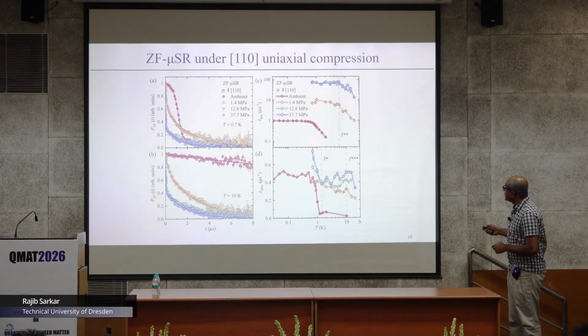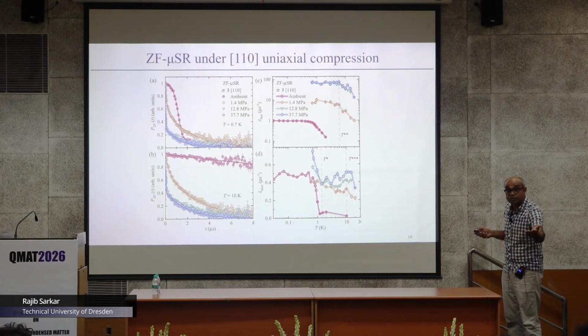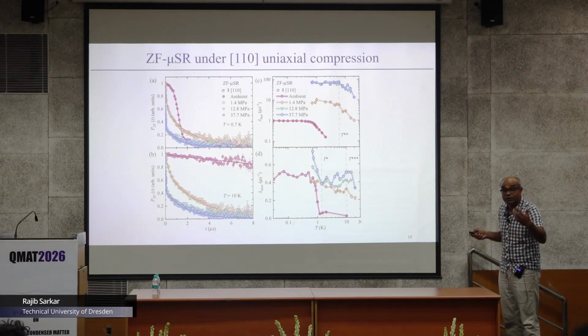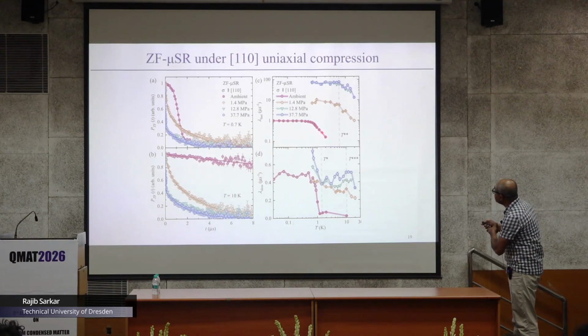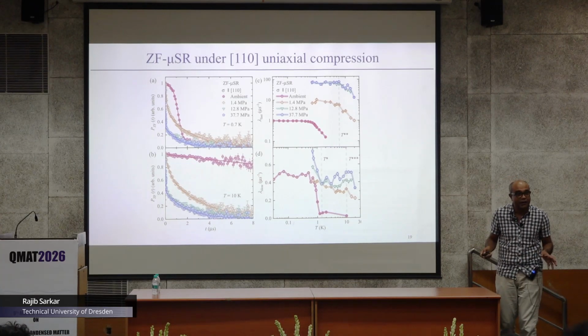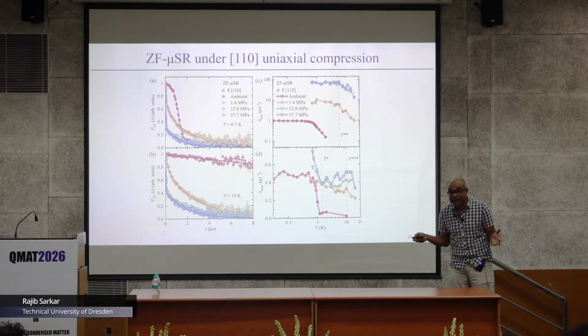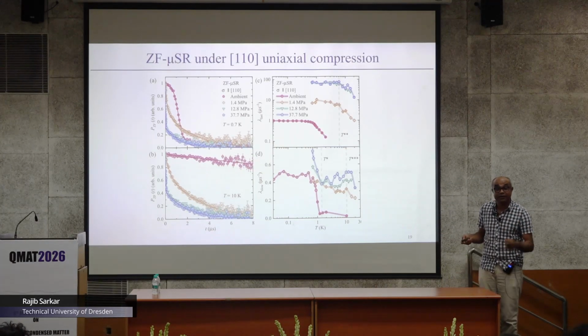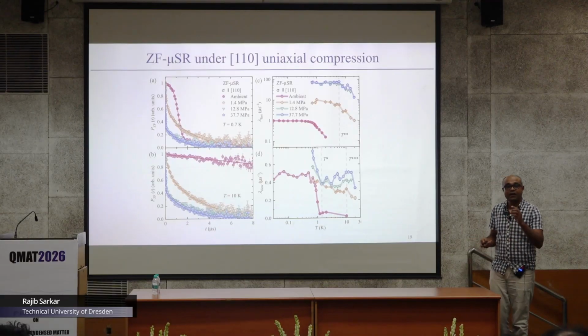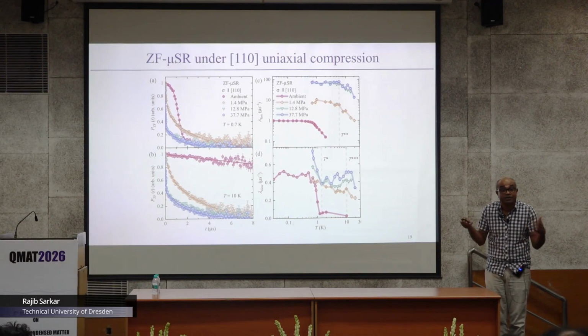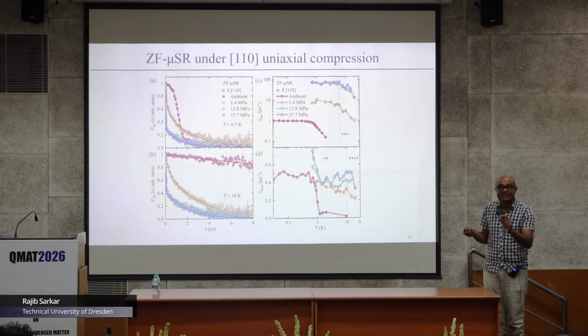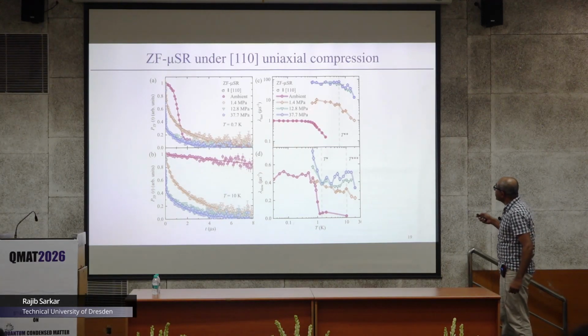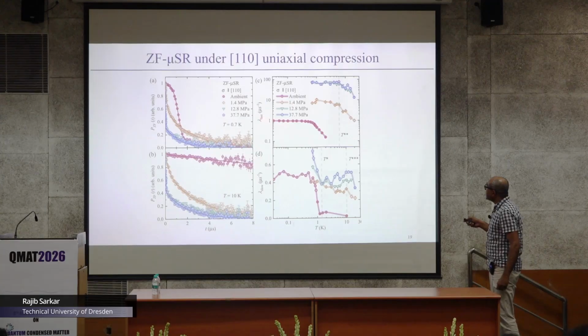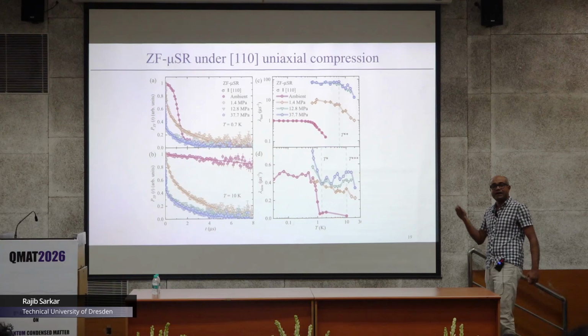And now if you really make a model and a fit, then you get a lambda, and also Moik showed the extraction of your lambda values. Now you see, this is my ambient pressure data, which is actually below 1 Kelvin. You have a constant relaxation value, which is actually your persistent spin dynamics. That is one signature, not the classical signature, but one signature of a quantum spin liquid state. You have the fluctuating ground state, or no static ordering. Now, as you increase the pressure, what you see, your lambda first is dramatically increased, going to at least 10 to the power 2 higher values.